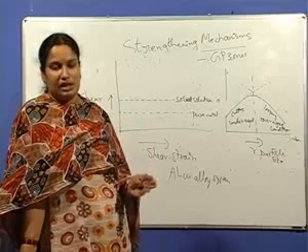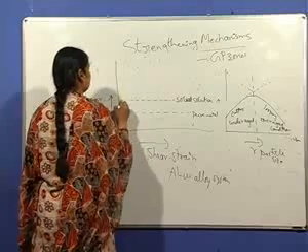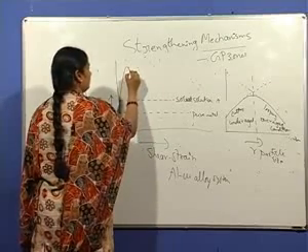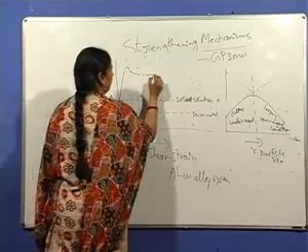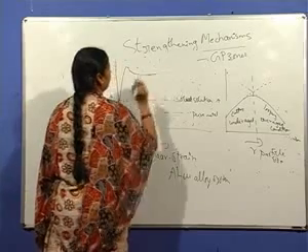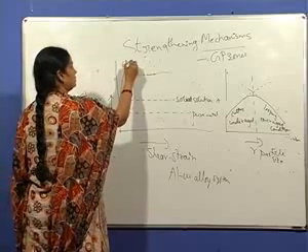When the alloy is aged to form the GP zones, an increase in yield strength occurs and slightly a yield drop occurs, and a low amount of strain hardening. This is for the case of GP zones.